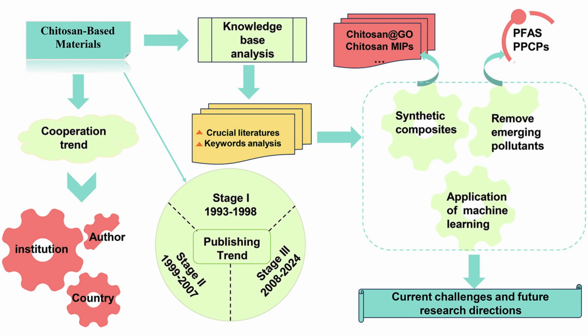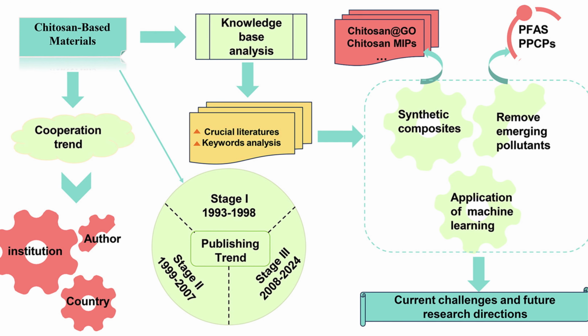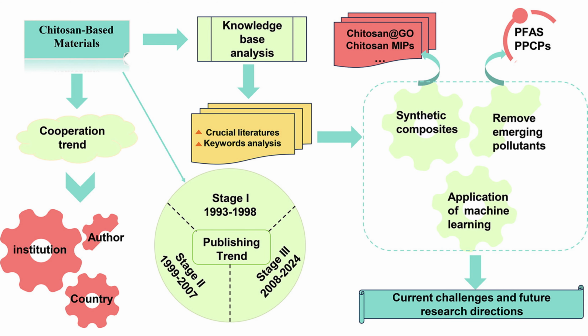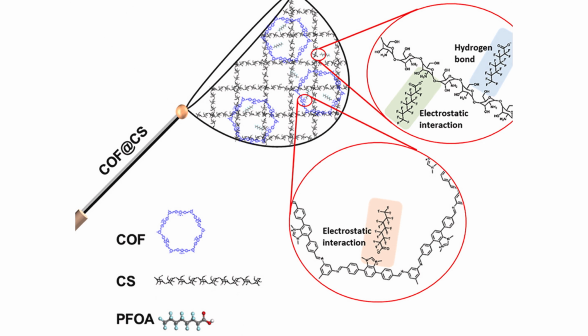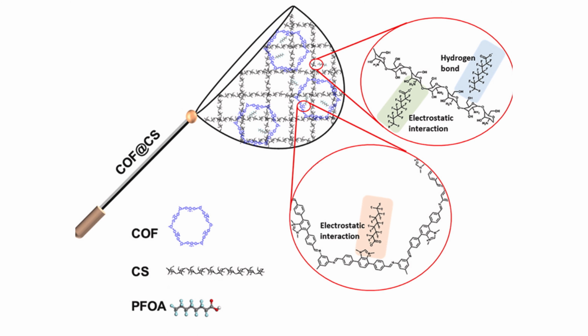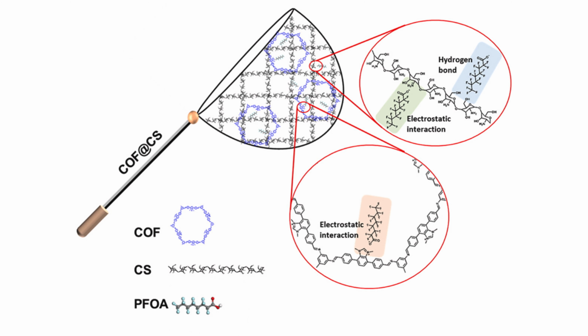Water treatment and environmental remediation. Heavy metals, dyes, pharmaceuticals, PFAS. Literature reviews confirm chitosan's dominance among bioadsorbents; selectivity and capacity scale with grafted chelators and cross-link density, PFAS specifically. Two strategies show promise. Cross-linked chitosan networks improve PFOS uptake while resisting swelling and leaching. Hybrid sorbents, covalent organic framework particles anchored on chitosan, markedly boost PFAS capture via hydrophobic/ionic sites.